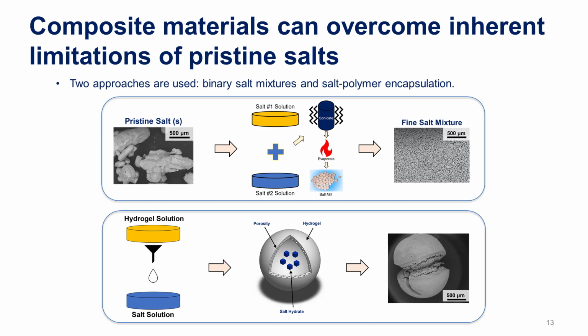The second thing we're doing is making an organic-inorganic composite. In this case, we have our salt solution, that's our inorganic material, and we work with hydrogels. This is our organic material, and we essentially just drip the hydrogel into the salt solution. Because these salts are divalent, it'll cross-link the hydrogel, and we can essentially encapsulate the salt. So the hydrogel forms this porous network, which holds the salt particles in place. So it's really just a scaffold.